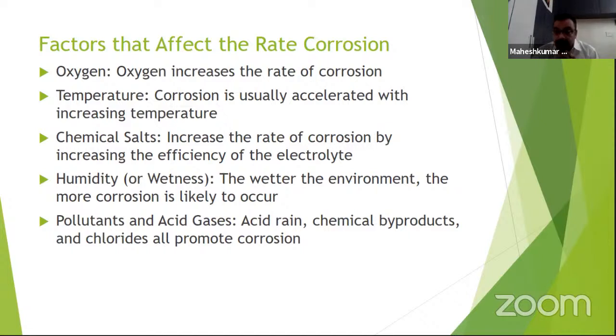Here, the temperature is also high. As the insulation is wicking the surface, it is also wicking the oxygen to it. Humidity is also being taken into consideration, making acid products such as hydrochloric acid or sulfuric acid by mixing with various gases. Humidity is also very high there, and when you have a thermal shock, condensation is also taking place. All these make the electrolyte under insulation very high in concentration and very high in temperature, and so the reaction is also very, very fast.